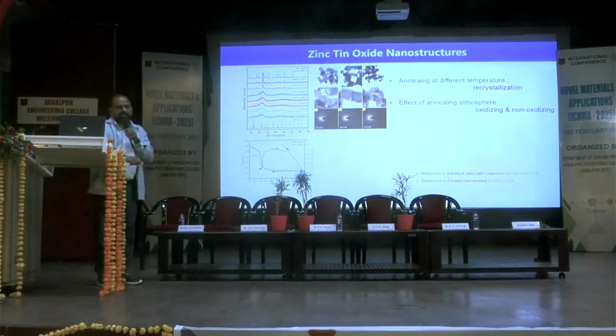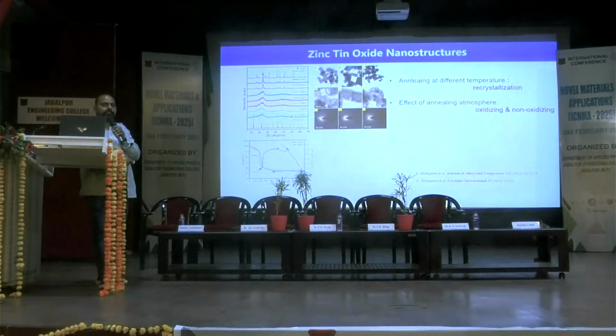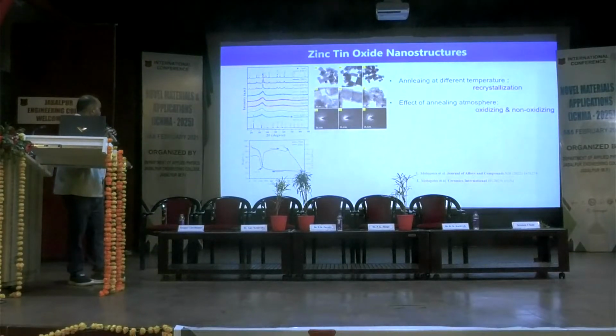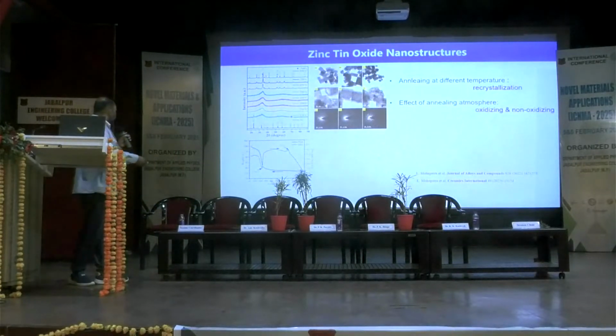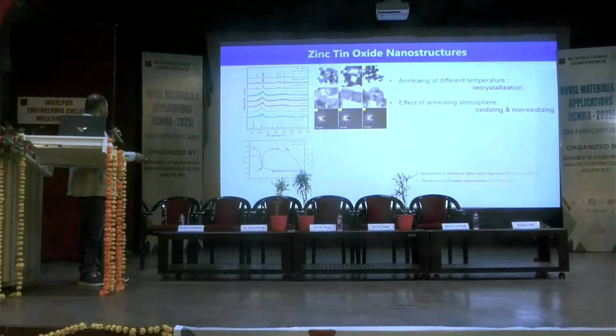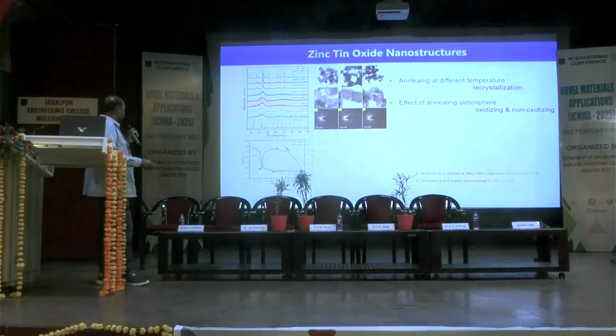That means there are very distinguished structural changes. We said that it basically transforms from the crystalline phase to an amorphous phase, and then again to another crystalline phase. You can see the selected area electron diffraction pattern also. This pattern is the as-grown sample. This is the intermediate, the 350 degrees Celsius heated sample, which shows the amorphous phase. And when we heat it again at almost 650, you can see that we restore the crystallinity, but in a different phase, and that is again visible here. So in this way we say that recrystallization happened.